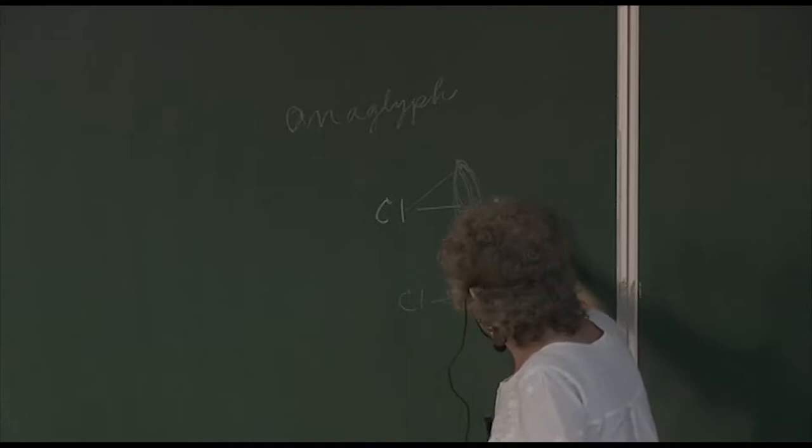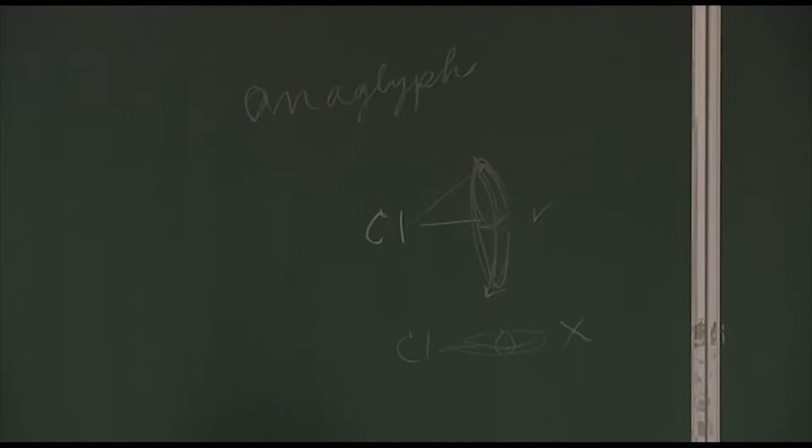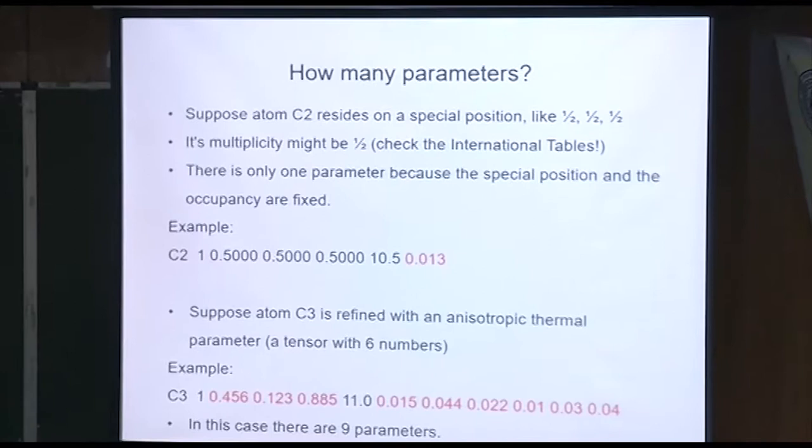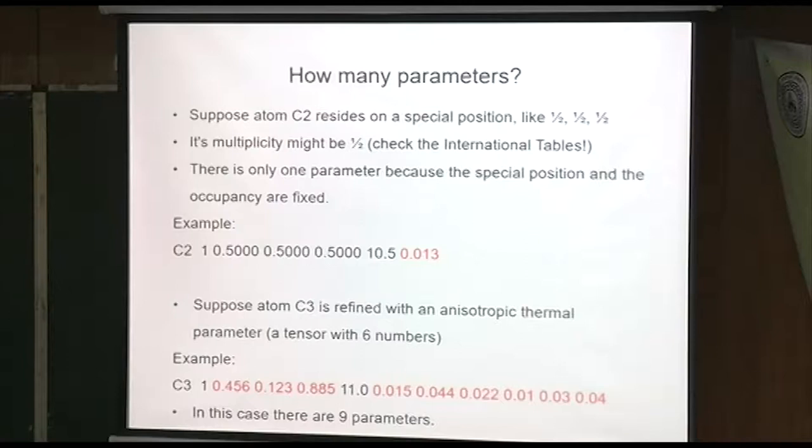It's giving a pretty accurate view of the shape of the electron density. U11, U22, U33 are parallel to the A, B, and C axes if you're in an orthonormal system. It is elongated in the direction of the libration. If you see them, instead of being like that, looking more like this, that's an alert. A CIF alert, and it means that there's something wrong with what you're doing. They should be perpendicular to the bond.